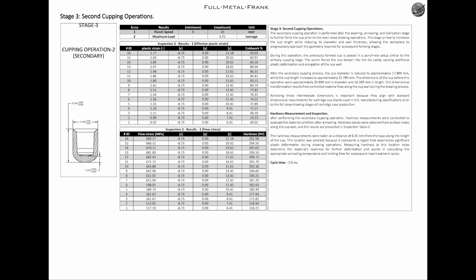During this operation, the previously formed cup is placed in a punch die setup similar to the primary cupping stage. The punch forces the cup deeper into the die cavity, causing additional plastic deformation and elongation of the cup wall. After the secondary cupping process, the cup diameter is reduced to approximately 17.800 millimeters, while the cup length increases to approximately 22.789 millimeters.